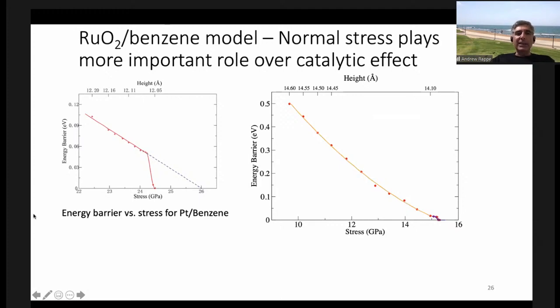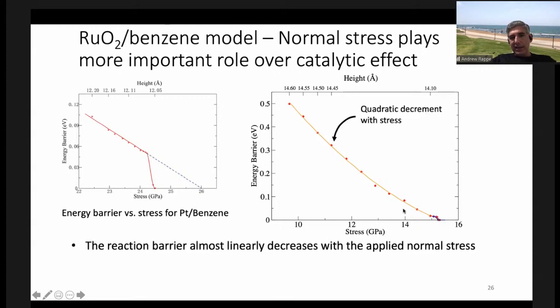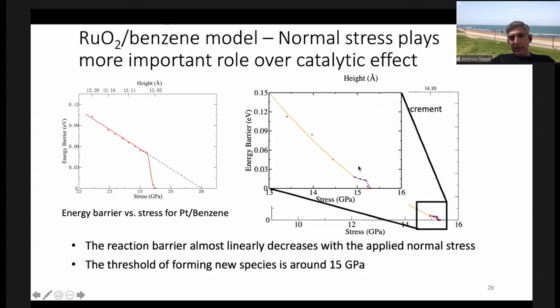Okay, now we do a side-by-side comparison. I already showed you this graph before. This is energy barrier versus stress. And we said there was a stress effect making it linear, and then there was the catalysis effect. Well, here it's a little bit curved, but it's basically linear. And the energy barrier goes down and down and down. And if there's any catalytic effect, we have to zoom in here to see it. And here, it's only teeny tiny. It would be just a small disruption in the otherwise linear trend. And so it's pretty much just the stress effect. The catalysis does not seem to be very important.